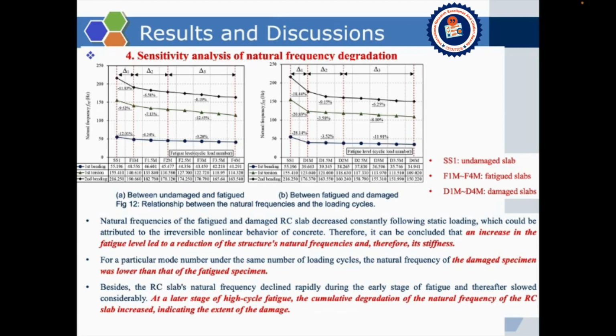Therefore, it could be concluded that an increase in the fatigue level leads to a reduction of the structure's natural frequency and therefore its stiffness. The comparison of results revealed that for a particular mode number under the same number of loading cycles, the natural frequency of the damaged slabs was lower than that of the fatigue specimen. Besides, the RC slab's natural frequency declined rapidly during the earlier stage of the fatigue and thereafter slowed considerably at a later stage of high-cycle fatigue. The cumulative decrease of the natural frequency of the RC slab increased, indicating the extent of the damage.